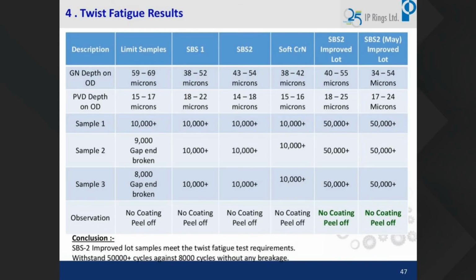See, I told you, initially when it broke, at that time the nitriding depth was very high, and because of the higher nitriding depth, because of the brittleness, the ring broke. Subsequently, we changed the diffusion pattern, and we reduced the diffusion time from 7.5 hours to 4 hours, and then we checked the twist fatigue. There was no coating peel off, as well as no breakage.